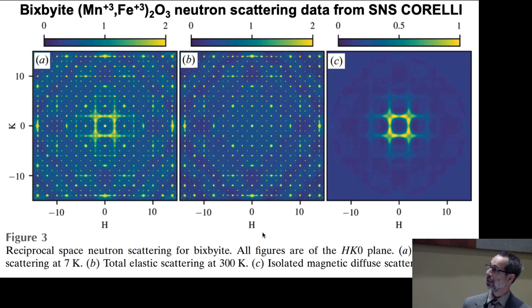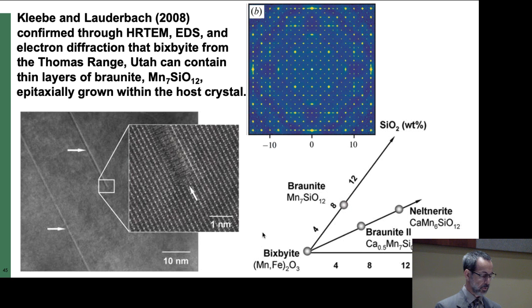Now, if you are keen-eyed, you can see that there is some diffuse scattering even at the high temperature. And the way we are interpreting that right now is that we think there's some epitaxial intergrowths of braunite, which is a manganese silicate that occurs in these natural crystals.